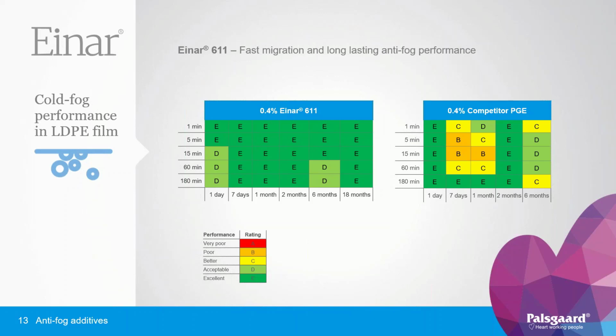Einar 611 is ideally suited for cold-extruded and laminated packaging films, where the antifog is often added to a very thin section of the entire film. It has a fast response and will remain efficient long-term, illustrated here by very good ratings 18 months after the film has been manufactured. Often, very little disturbance can tip results out of the required performance window. Here illustrated by results from competing PGE chemistry that may work well in a conventional PE packaging, but when challenged, results start to fall behind.